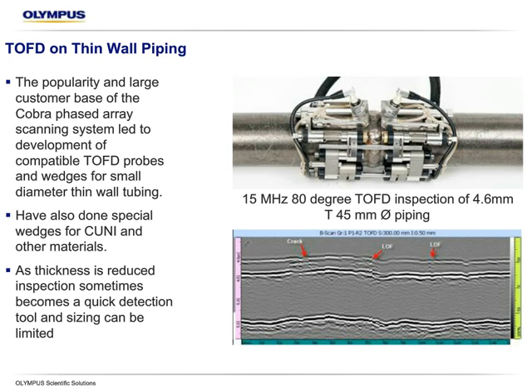One consideration as we get thinner with all ultrasonic materials is at some point it becomes maybe a go, no-go inspection. So the ability to accurately size things due to the relationship of the thickness and the size of the flaws versus the beam might not be possible or might not be as accurate. So we can see a variety of defects there shown, cracks, lack of fusion in a very thin material, but we may not be able to size those. We might just say, yes, there's a crack there. We've also had a lot of success with this application with some varying materials like copper nickel.